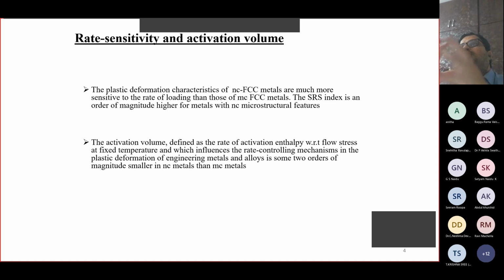these lattice defects control the mechanics of plasticity. But to understand what sort of defects have participated in a given plastic deformation event, you need to evaluate some parameter called activation volume. So if the activation volume is reasonably high, then dislocations are the chief controllers of plastic deformation, in which case your material microstructure is like a grain size of tens of microns. Whereas if you bring it down to less than 100 nanometers, then your activation volume also comes down because grain boundaries and other lattice defects play a role in dictating the mechanics of plasticity.